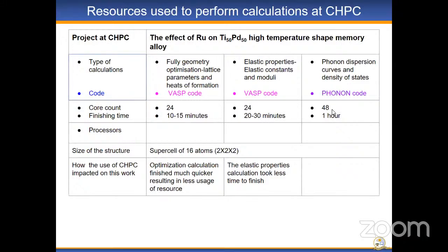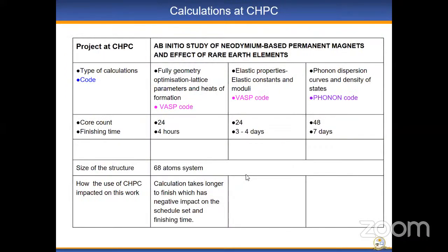But for the phonon calculations, it can take about an hour, but that is the 48 core. What I should emphasize here is that with the phonon code, it depends on how big the supercell is that is generated. But if you were to use any other or normal computing, where it takes 1 hour, you might take more than 2 or 3 days to achieve this calculation. So what I want to indicate is that you can see here with the elastic constants calculation, it takes less time.